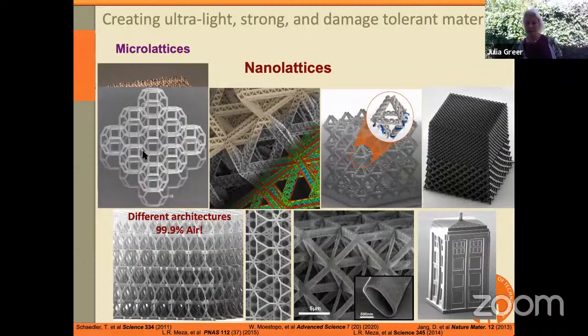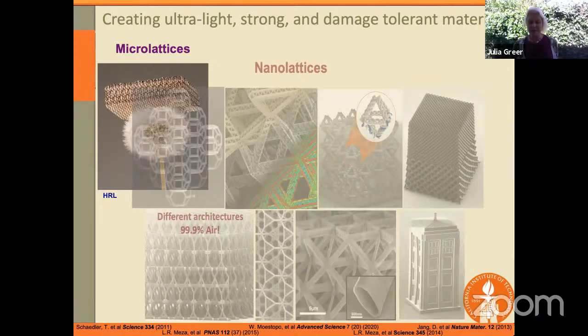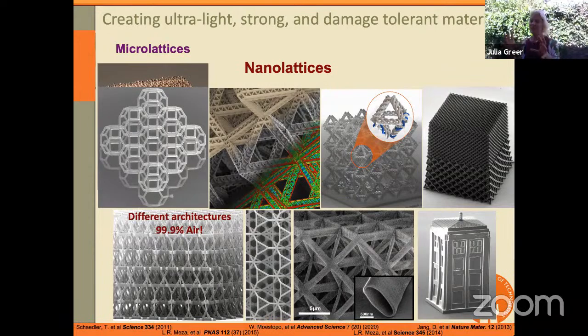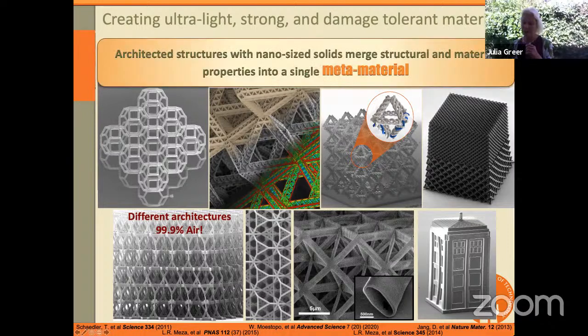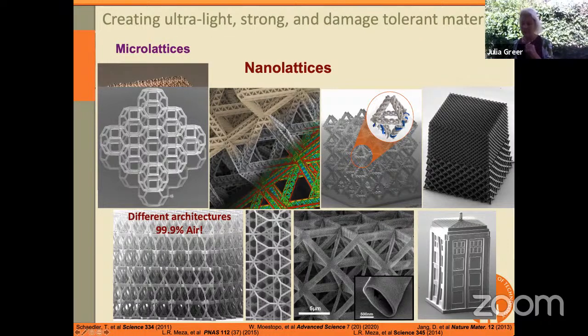There's an obvious level of porosity here. As you can see, they're very open. They're called cellular solids. And so because of that, they contain about 99.9% air, because you can see these are very open architectures. Now, the less obvious level of porosity, of course, is this: many of these architectures are comprised of an interwoven network of hollow tubes. And the tubes are hollow on the inside. And so the largest dimension of the solid at any location is just the wall thickness of each of these tubes, which can be on the order of 5 or 10 nanometers. So you can imagine that this single material embodies every length scale from 5 nanometers to hundreds of nanometers to microns and eventually millimeters and centimeters.